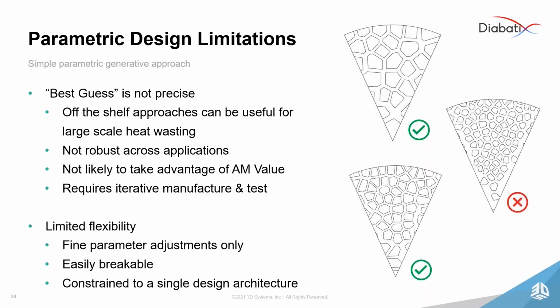And as you can see on the right, here's a design architecture that has some parameter adjustments associated with it, and you can see it being easily broken when parameters pass a threshold value. So that traditional best guess approach is not ideal for precision cooling requirements or high productivity cooling requirements. It also doesn't take advantage of the value of additive manufacturing. To some degree, it may, but this design here is easily machinable. But then again, if you go to machining, you have to deal with traditional assembly and welding for consolidation of the design. And this does require a lot of lead time for traditional manufacturing, testing, simulation, and a lot of people involved in order to validate that design.